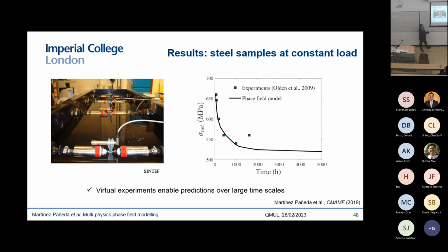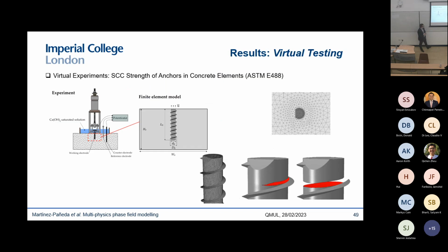But we can use our model not only to reproduce experiments and gain confidence in our predictions, but also to run virtual experiments over very large timescales. This is the key point. So we can determine what is this critical threshold below which we won't see any hydrogen embrittlement. And in general, we can model anything we want. So this is a classic standardized test from the ASTM standard, where you look into the failure of a screw that is exposed to an aggressive environment. So you have a metallic screw inside of a concrete plate, and you can see here that we can capture the full rupture of the screw.